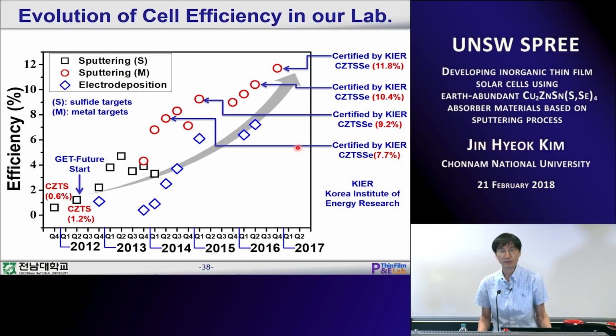And in the last 5 years in our lab, we increased our cell efficiency from 0.6% up to 11.8%. In the beginning, we started with pure sulfide, and we also used sulfide targets. We used zinc sulfide, tin sulfide, and copper, so 3 different targets. But we had many difficulties in improving cell efficiencies. So we changed the target, and we also put sulfur and selenium together. So we could improve our cell efficiency up to 11.8%.